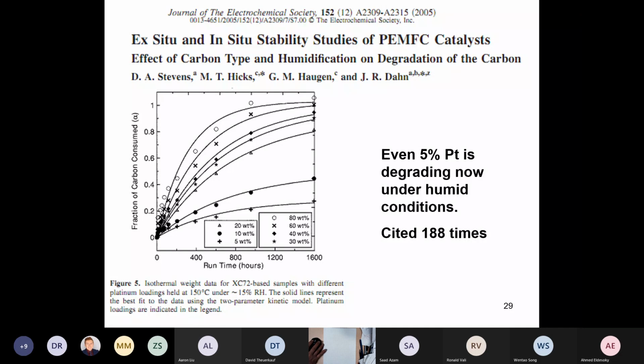So the question was, okay, this is happening in a period of a month or so at 150 degrees C. How fast does it actually happen in a fuel cell running at 80 degrees or 90 degrees C? And you have to think for a minute about, okay, well, fine, what even happens if you have carbon consumption? I mean, who cares, right? The platinum's still there, this catalyst is still there, so does this even matter?